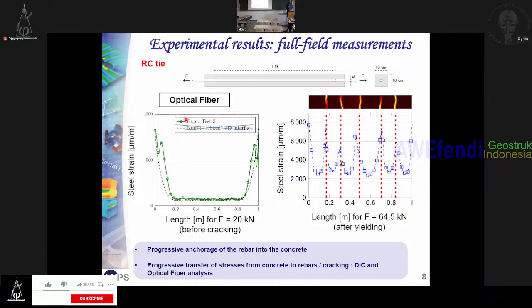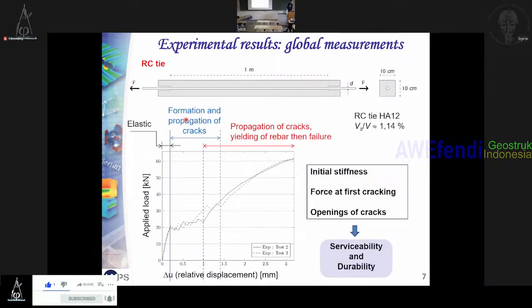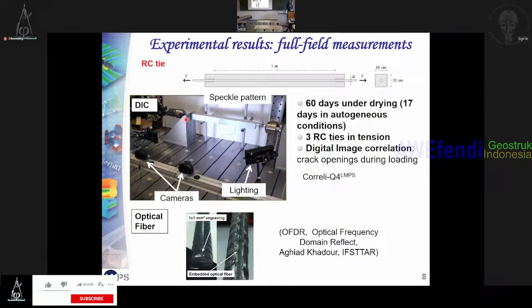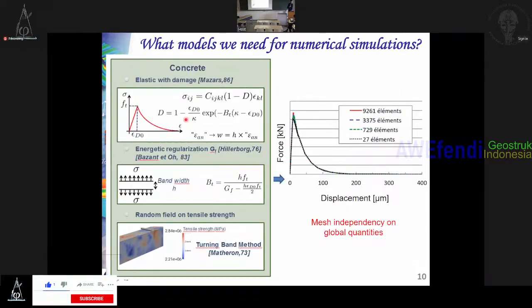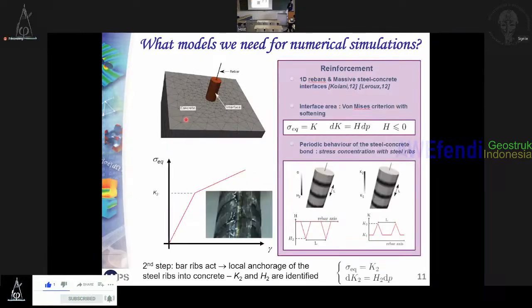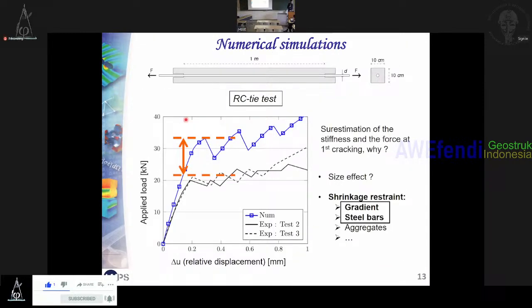Of course, not putting anything in question, your specimen is 10 by 10, precisely this specimen that we are seeing. You left it 17 days in autogenous condition and 60 days drying. Sixty days drying for a 10 centimeter specimen is not enough for the complete drying to happen. So, did you do the experiment in a very small time? You have two tests, and maybe they give you different results because one waited more than the other. And just to finish my question, the moisture profiling within the specimen, is this something your models are accounting for? Can you comment a little bit?